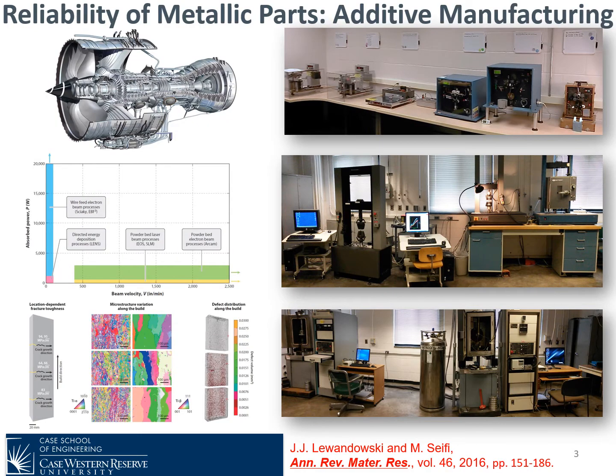If I were to look at, in particular, the reliability of metallic parts in the additive manufacturing area, you could imagine a number of different parts. One of the areas that we've gotten involved with is jet engine components, like materials for blades, as shown here. In this particular case, depending on the additive technique that you use, there are different power velocity regimes. And as you can imagine, depending where you are in this power velocity regime, you could get very different microstructures, properties, and defect densities.